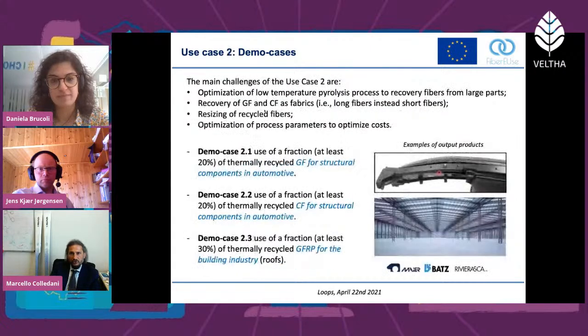I will jump directly to the second strategy, which is more traditional for carbon fiber, although we are innovating the process we are using for obtaining reusable, cleaned carbon fibers. The strategy here is to use thermochemical processes, basically pyrolysis. It's not the usual pyrolysis. We use environment-controlled pyrolysis with the addition of gas that makes the pyrolysis more efficient and gives the possibility to recover both the fibers and the resin. We apply this strategy both to carbon fiber components in the automotive industry, where M4R and BATZ are producing their demonstrators, and in the construction industry, targeting long glass fibers in roofing applications.